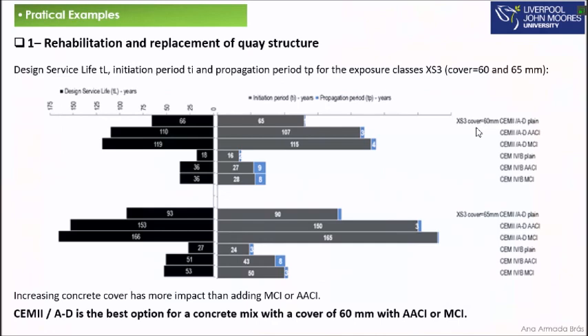So we did the service life calculation. This graphic here presents the design service life, which are the black bars, for each concrete composition with or without corrosion inhibitors. And on your right, you have the initiation period. So basically, design service life is the sum of the initiation period and the propagation period. You can see that the initiation period is the gray bar, and the small ones, the blue ones, are the propagation period. And this graphic is only for the exposure class XS3.